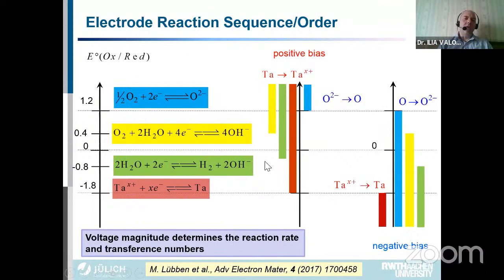Then if we increase the positive potential, the second reaction will take place. If we further increase the voltage, we'll also have this reaction at the end, at very high positive potentials, where oxygen will be oxidized to form an oxygen molecule. The same applies for the reduction, but in the other direction. Reduced first will be the elements with the most positive potential. In that case, if we have molecular or atomic oxygen, this will be the reaction that will first take place. Then, increasing the negative voltage, we'll start to reduce oxygen in the presence of moisture, or then we'll reduce water.